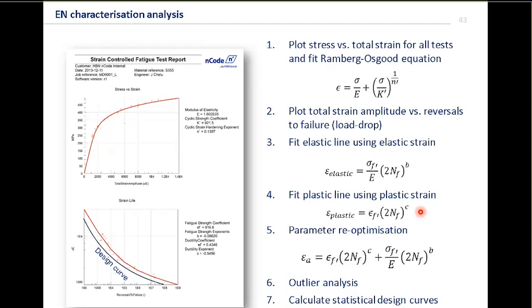Now, typically, what we need to then do is add them together, and they usually add together quite nicely to fit the entire curve, but we usually do a little bit of re-optimization on these parameters, just so it fits better, especially in the middle where the two are added together. Once we've got a good fit, we then start to do an outlier analysis.